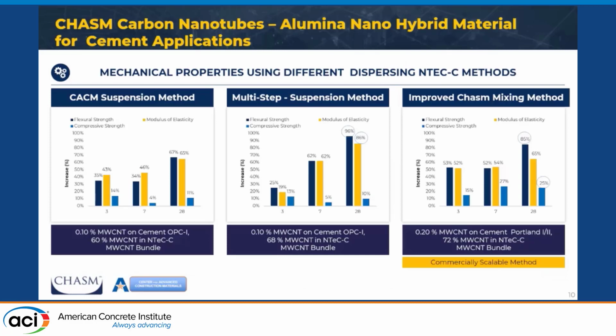In this slide, I am comparing different ways to disperse nanotube in the cement, and you can observe the suspension method, the combination of the suspension method plus the Chasm dispersion method, which is a multi-step method, and our improved method. What happened is when we combine the suspension with Chasm technology, we observe a very strong increase in flexural strength and also in modulus of elasticity. However, the compressive strength remained lower, at the level of 10%. However, the only method that is scalable at commercial scale is the improved Chasm mixing method.